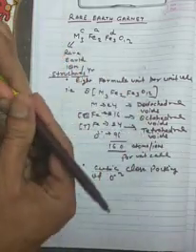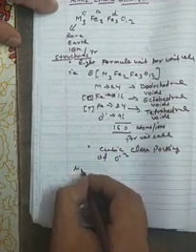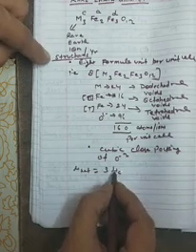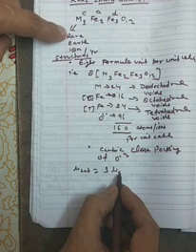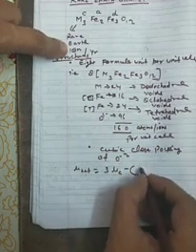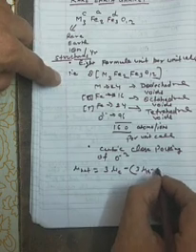Now how will you calculate the net magnetic moment? Let me write over here: net. Let mu c be the magnetic moment due to the rare earth ion or yttrium ion. Then you have to subtract the contribution from the d site, tetrahedrally coordinated iron in 3 plus state, minus 2 mu d.